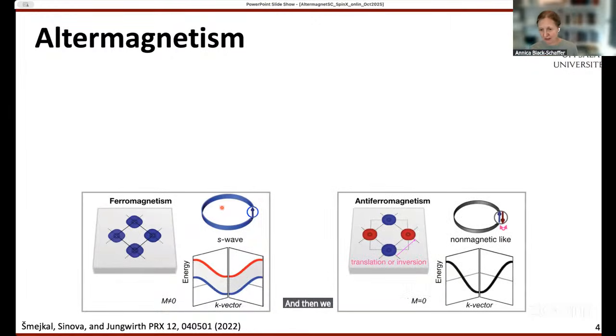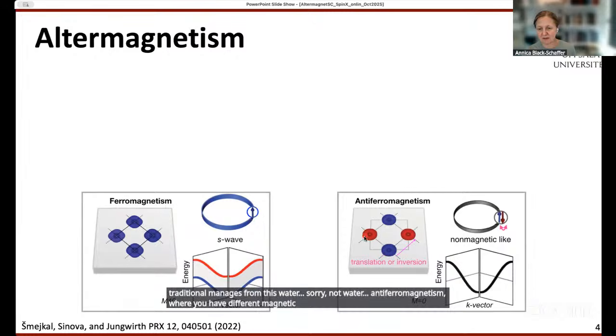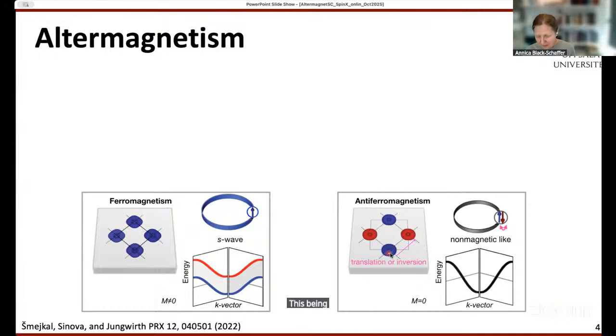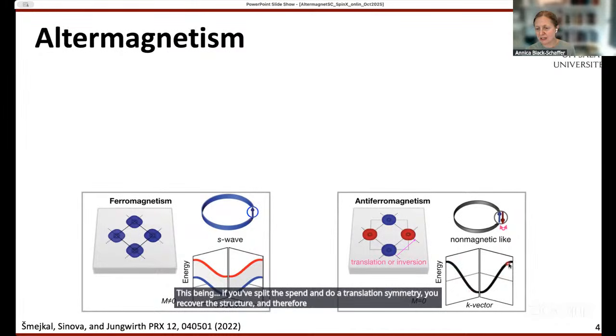And then we have, of course, the other type of traditional magnetism, antiferromagnetism, where you have different magnetic moments on neighboring sites. So this blue is spin up, and red is spin down. If you split the spin and do a translation symmetry, you recover the structure, and therefore you have a spin-degenerate band structure. So you actually don't see any magnetic moment on the Fermi surface like this.